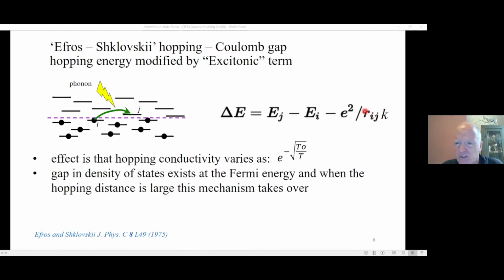Now, if this was an actual exciton, this distance would be something like the Bohr radius. But in the hopping regime, it's actually the hopping distance, so it can be quite a small energy correction. And that changes the hopping conductivity. The power here becomes a half. That was published in 1975, Efros-Shklovskii.